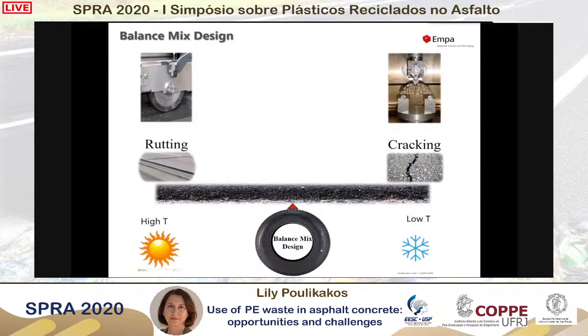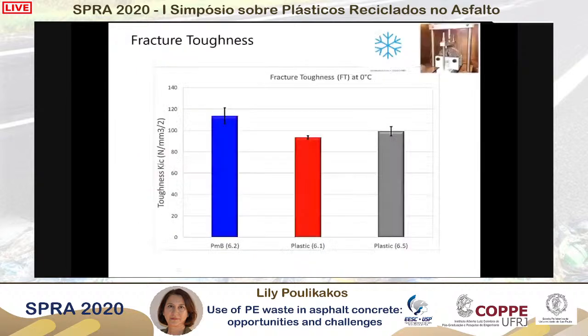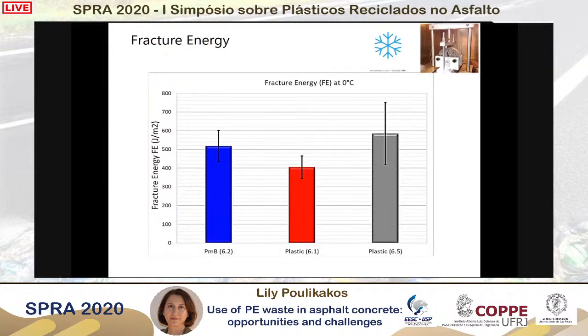So far we have looked at the cracking performance and the high temperature performance of the mixtures. So the two ends: at low temperatures, the material can be prone to cracking, and at high temperatures, it can be prone to rutting. And so we have looked at behavior at these two ends. We have other experiments that are also planned. So far, the results at the low temperature end, comparing the polymer modified mixture with the two plastic mixtures, show similar fracture toughness, I would say, at 0 degrees for both of the plastic modified mixtures. And if we look at the fracture energy, even the plastic modified mixture that had more binder performed a bit better.